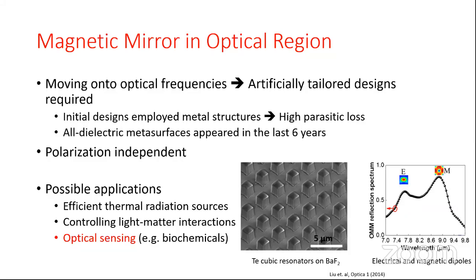proposed using metal structures. And by the way, there is no natural material that has interesting magnetic properties. So we have to artificially tailor the designs ourselves, and that tends to require microfabrication or even nanofabrication. The problem with metal structures is high parasitic loss, so we tend to lose a lot of the optical wave in terms of absorption. But in the last 6 years, all-dielectric metasurfaces appeared in the literature. One huge advantage of using a magnetic mirror is that it is polarization independent.